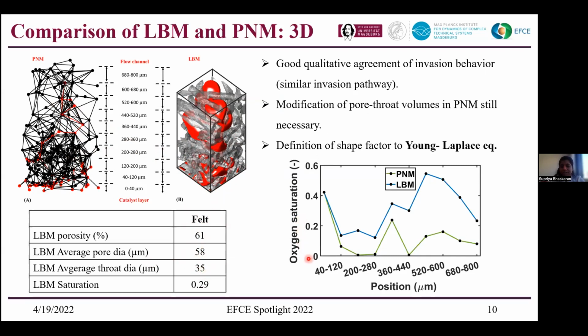As you can see here, the oxygen saturation across the height of the PTL, we could see a similar trend for both PNM as well as LBM. But there is a magnitude difference between the PNM and LBM. This is due to the inefficient derivation of the pores and throats that we derive from our porous structure. So a lot of focus right now is on how we can modify this pore throat volumes in PNM so that we could match this difference in the saturation values and the pore volumes.